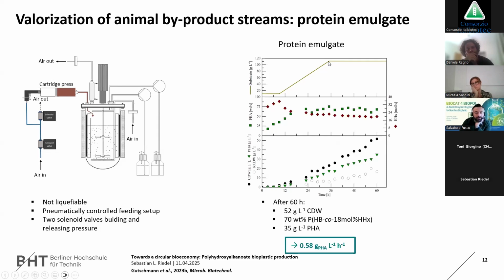Here on top you see the feeding, and what was also interesting is that over the whole time the cells were full with PHA. This is due to the cells also being able to use the amino acids from the protein hydrolysate, and we didn't feed any extra nitrogen into the system, so the cells were triggered through nitrogen limitation to produce a lot. With every feed bolus they got carbon and nitrogen, and then they were nitrogen limited all the time. We are thinking to use this maybe as a continuous feeding strategy.